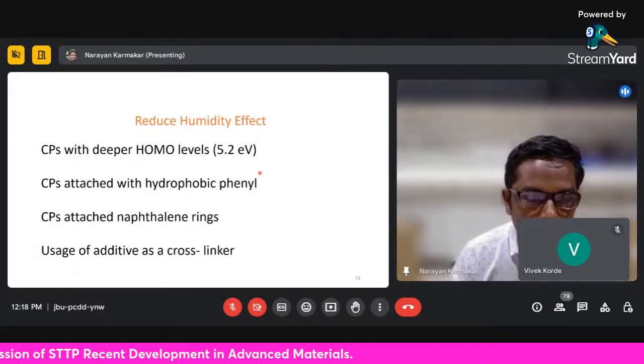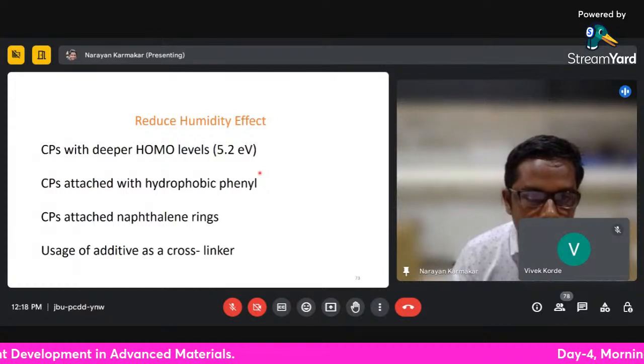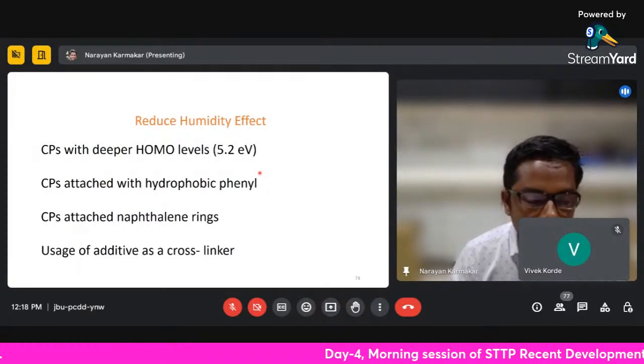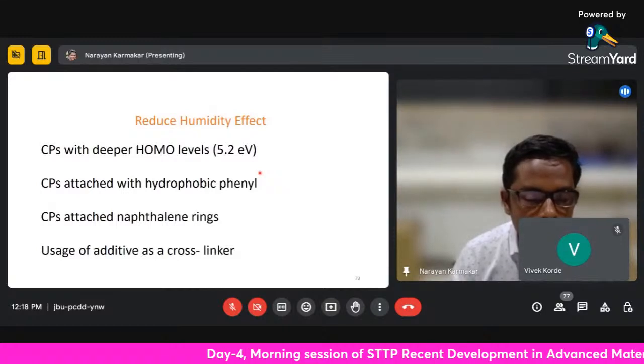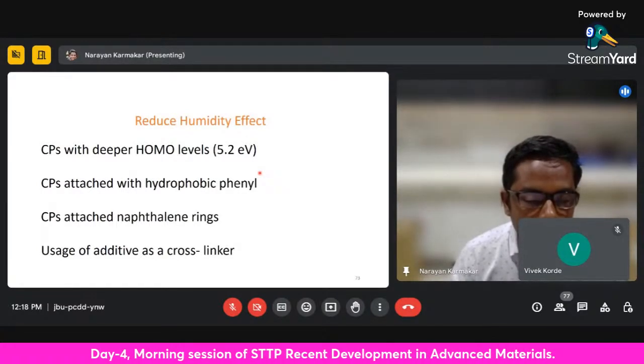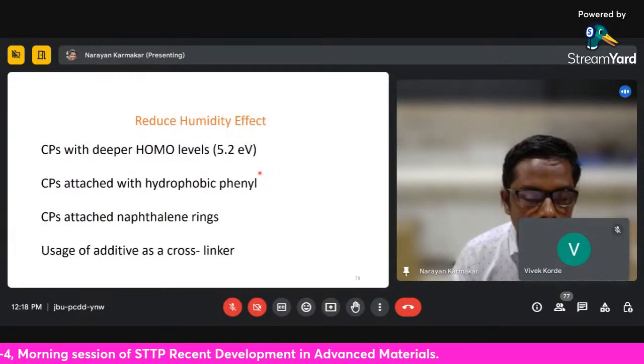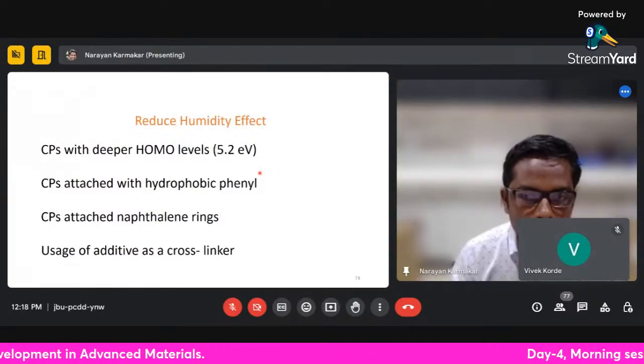Because when you try to reduce the humidity effect of the conducting polymer, you compromise on the selectivity or sensitivity of the gas sensor. So we need to properly balance between the two: the humidity effect and the sensitivity effect.